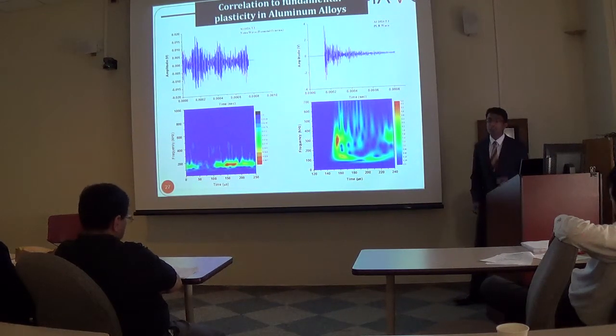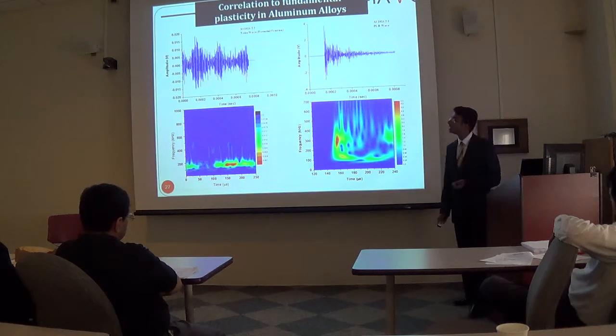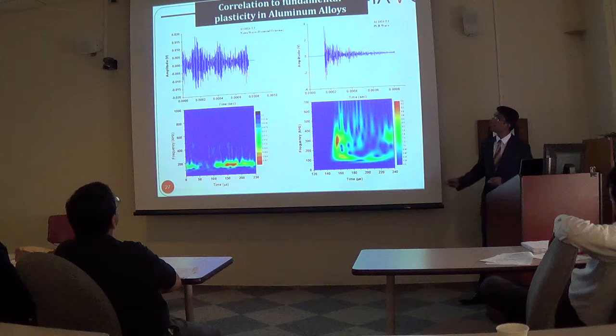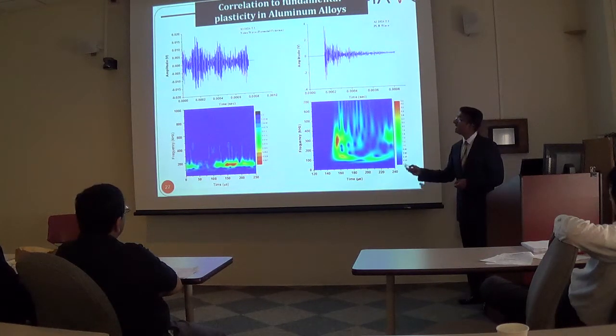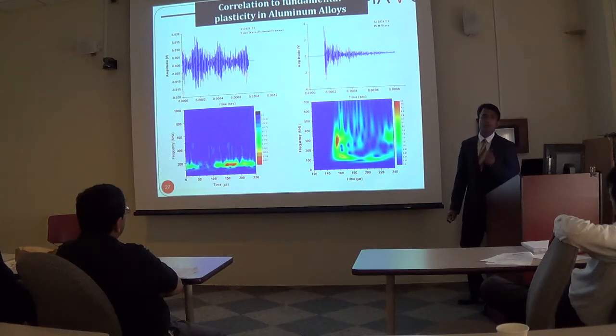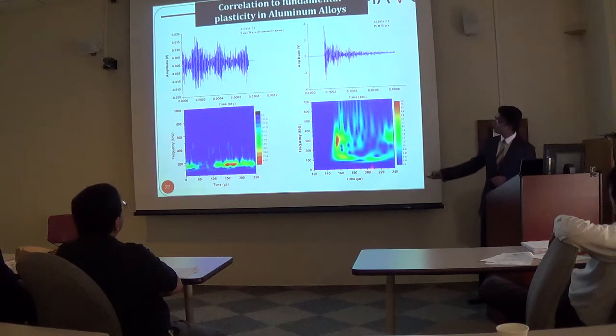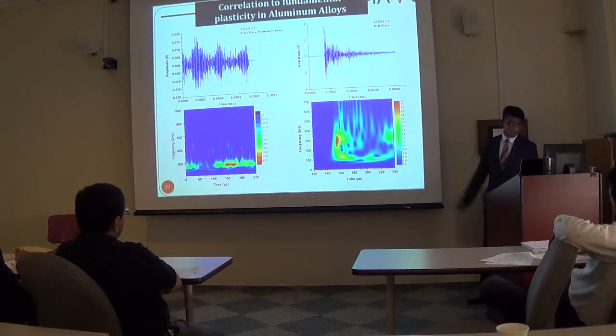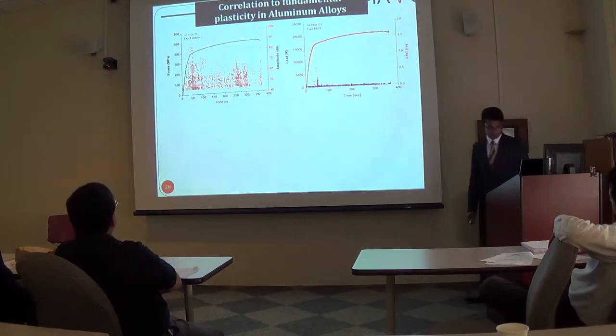Now, in accordance with the ASTM standard E976, PLB tests were performed on these specimens to calibrate the sensitivity of the sensors. And it can be seen that the PLB waveforms again have very similar characteristics to the ones that were shown previously. You can see the frequency analysis indeed shows the initial high frequency and the subsequent low frequency.